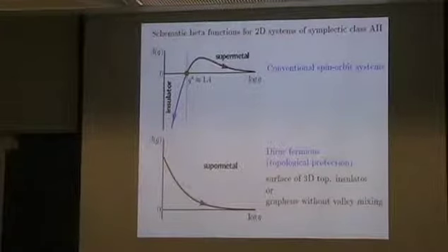So what's super about the super metal? What's the experimental manifestation? Oh, the conductivity is infinite. In 3D, you will flow to finite conductivity. Right. And here you flow to infinite conductivity. So in 3D, of course, you also flow to infinite conductance, but the conductivity will be finite, right? It will be just a normal metal. So here in 2D, conductance and conductivity are the same, so you flow to infinite conductivity. I mean, it's just a word. If you don't like it, it's confusing. It's a metal with an infinite fixed point conductivity.